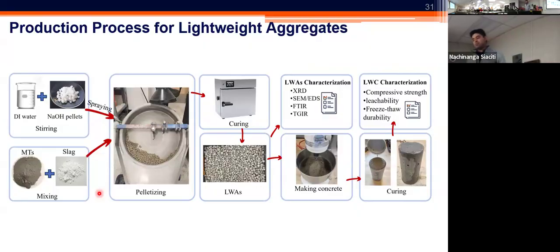So fairly similar in terms of the chemistry for this whole process, where the mine tailings are often mixed with some additional supplements, then mixed with the sodium hydroxide solution that gets sprayed on the pelletizer, and the material then goes through a curing oven, and then you will be left with the finally cured and ready to use type of a lightweight aggregate that can be incorporated in the structure of the concrete.